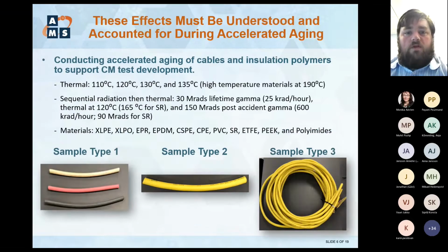So the work we're doing is basically to develop condition monitoring tools and, in essence, look at these different aging effects, because we have to develop these CM techniques to compare data between tests. We've done testing and are continuing to do testing at a wide range of temperatures. We're doing thermal only exposure of a lot of polymers at 120 degrees Celsius, 110, 130, 135.